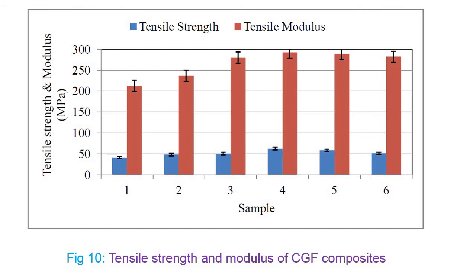Nearly 41 megapascal to 58 megapascal. And tensile modulus, you can see, we will get nearly 212 megapascal to 292 megapascal. Tensile modulus is the ratio of stress along an axis to strain along that axis. You guys know what stress is: stress is nothing but force per unit area. Strain is the ratio of deformation over initial length. These are basic level. We will get nearly 212 megapascal to 292 megapascal as the tensile modulus.